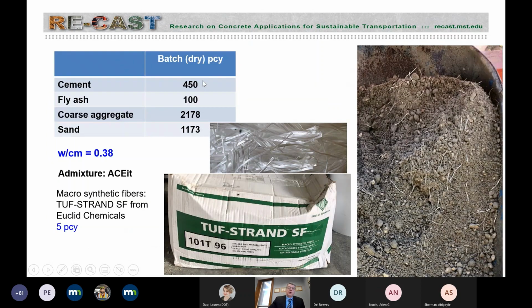So this is a mixture proportioning. In the previous case study I mentioned in Mexico, Missouri, only 450 pounds per cubic yard of cement was used. In this case, it was decided to use also fly ash, so a lot higher paste content, or binder content, but the water binder ratio was tighter. So instead of 0.53, it was reduced to 0.38.